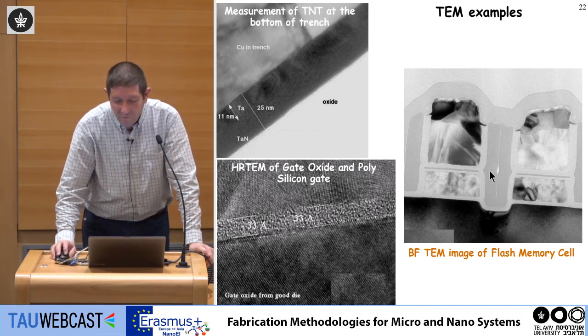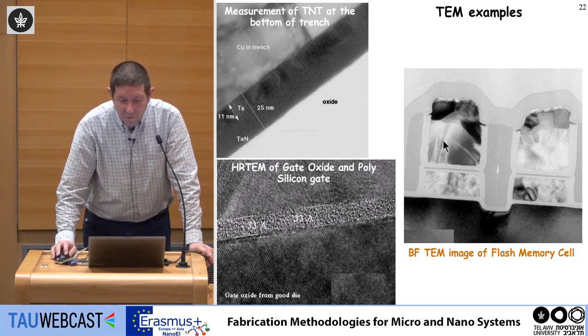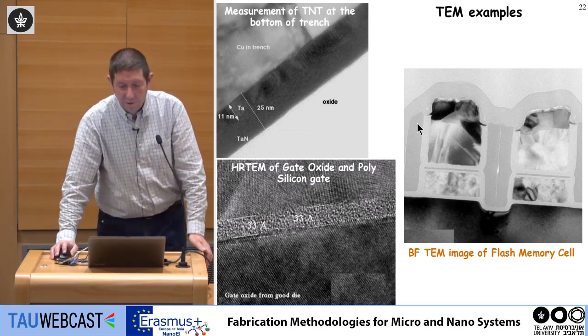Do you see it here? This is the metal, and as you can see here, sorry, this is polysilicon. So this is an isolation between two transistors, and they filled it with poly, and you see that there's a little void here in the center. But these are, you can see the high resolution imaging of the TEM.